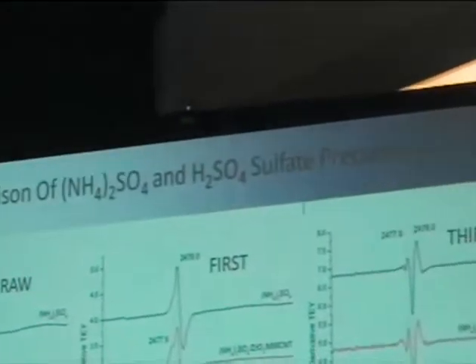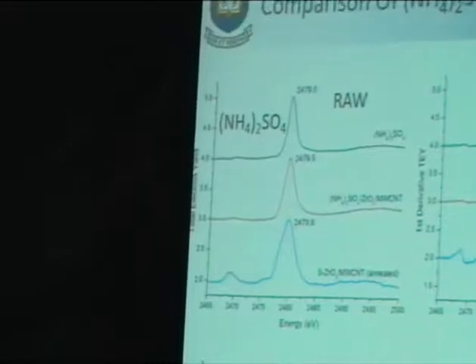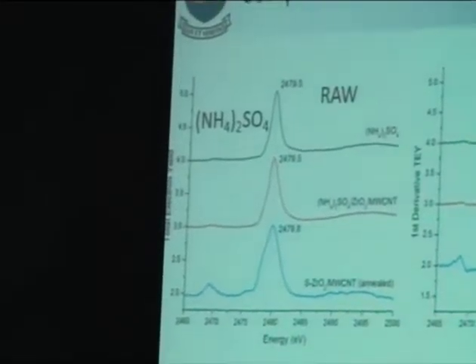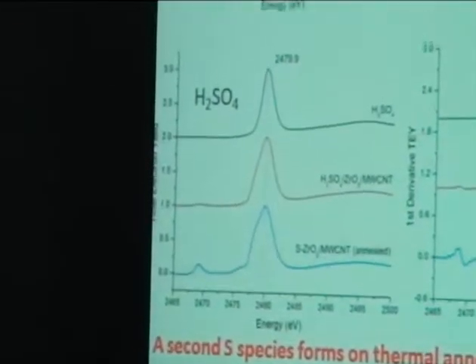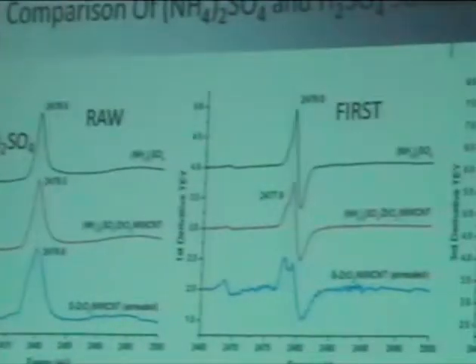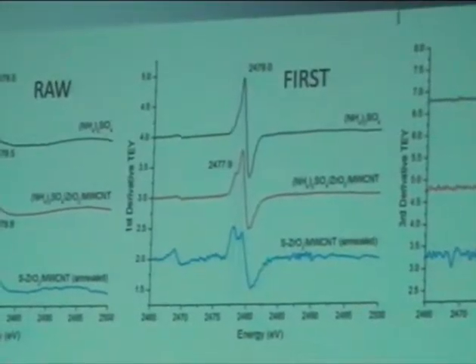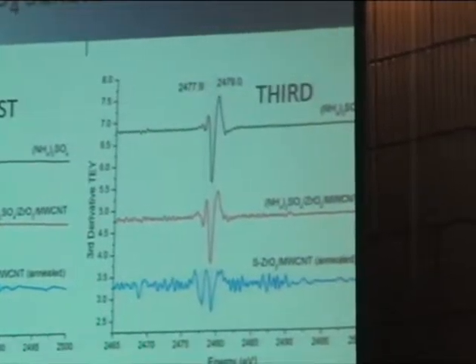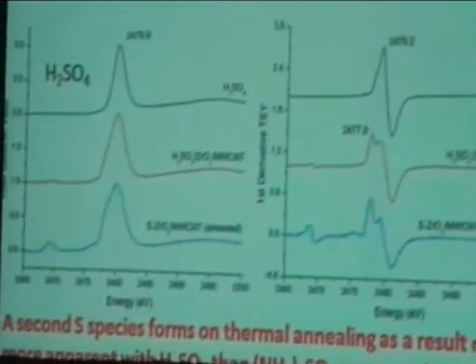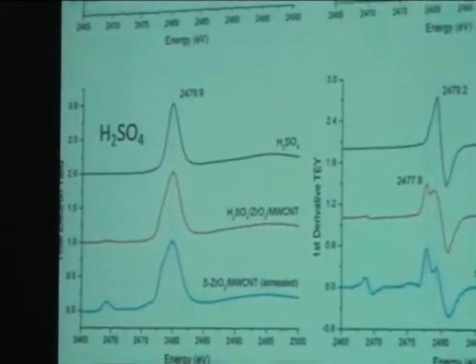Now, this is another complicated slide. But basically what I'm going to do is to use two different sulfate precursors, ammonium sulfate and sulfuric acid, and try to convince you that you actually have two different species, the sulfate species and this new species that comes about from the interaction with zirconia. And it's hard to see much going on when you just look at the raw data. That is the precursor, the ammonium sulfate that was impregnated. This is after it's impregnated.